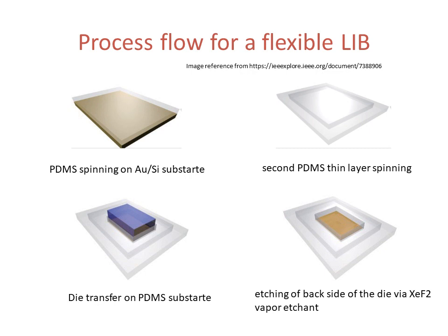After that PDMS spinning, the die with the lithium ion battery stack is placed upside down facing the PDMS thin layer and cured at room temperature for 24 hours, which we can see in the figure, die transfer on PDMS substrate. After PDMS curing, the exposed silicon substrate can be further processed with xenon difluoride, which we can see in the last figure.